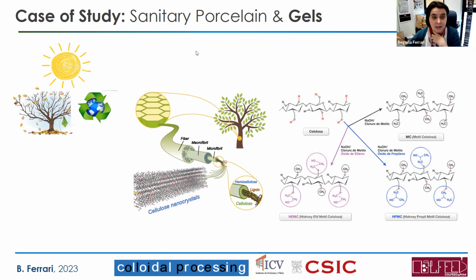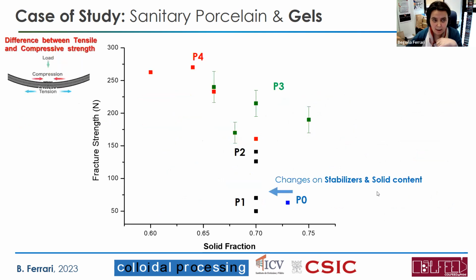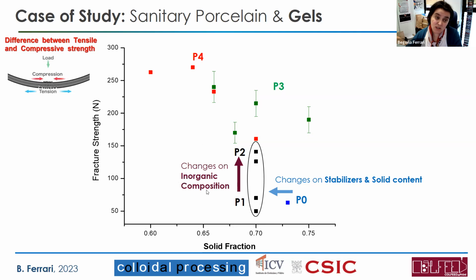This is, again, the case of a study of sanitary porcelains using gels, right? You see here in this diagram the mechanical properties, in this case the fracture strength, with the evolution of different kinds of pieces, with the solid concentration that we use in the suspension. So when we change the stabilizer and the solid content of the material, we are at the same fracture strength, but we are using less material in the suspension, having exactly the same fracture strength. And this is because we are using the right stabilizer, right? By the time that we change the inorganic composition, choosing very good raw material, we can improve the structural strength without changing the solid fraction of the suspension.